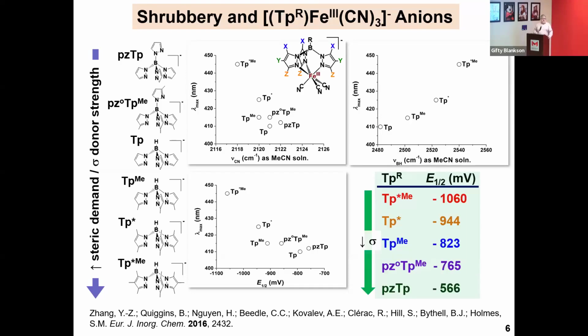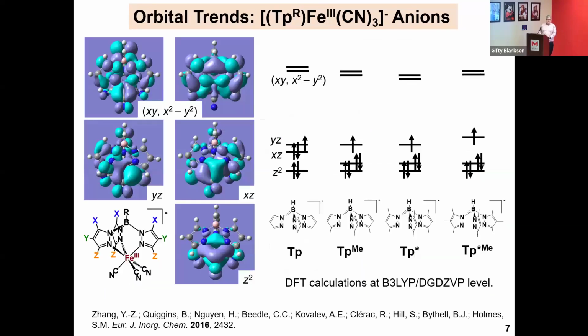But summarizing a lot of the data, as you decrease the donor ability of the pyrazolylborate ligand, you increase the cyanide stretch, at least in solution. You increase the energy of that charge transfer absorption called lambda max, and you decrease simultaneously the energy of the BH stretch. For those who like density functional theory calculations, you can do that. It gives you additional information about where things are in energy.